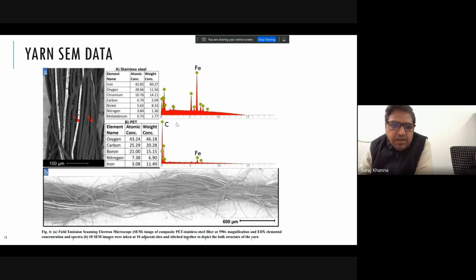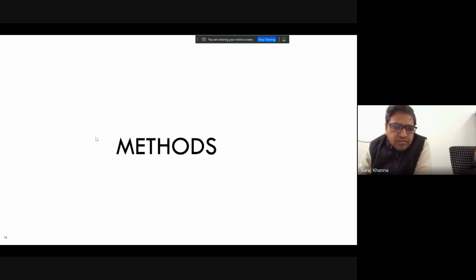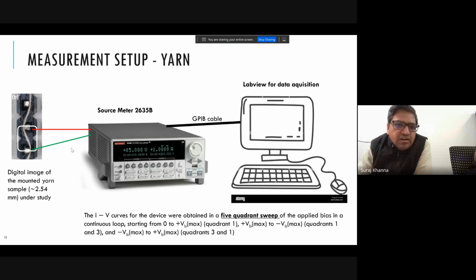Okay, this is the SEM data. You can see the composition of stainless steel and PET fibers across the data. The bright spots are stainless steel, and the darker spots are PET fibers. So we have measured this.